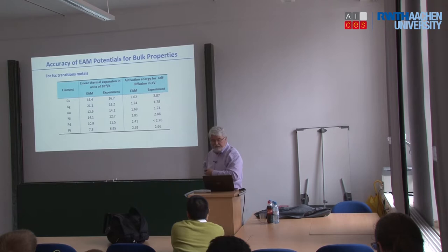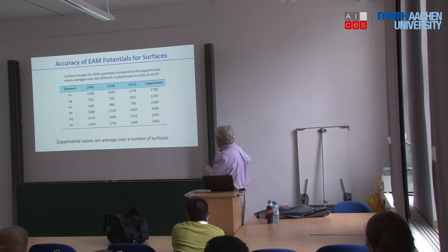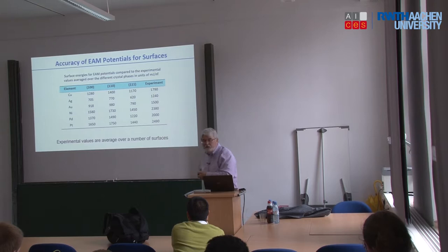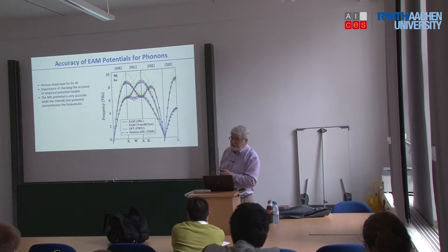How about surface energies? Well, we can calculate surface energies with EAM. And the agreement's not so good by any means. But these experiments are very, very difficult to do, and they're averaged over a whole bunch of surfaces. So these experimental numbers are pretty poorly understood, even for something like the surface energy of copper, which you would think would have been done 100 years ago. It's still not really well understood. So the EAM may actually be doing quite a good job here. These are the phonons.